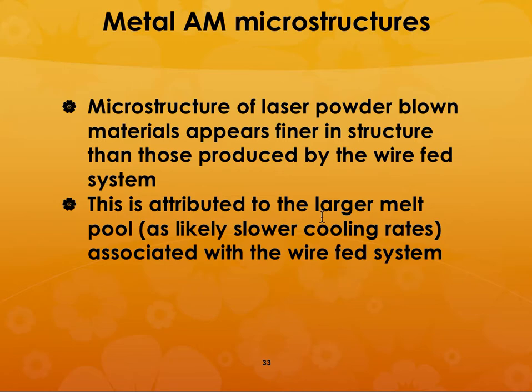In this case, the laser powder blown material appears finer in structure than those produced by the wire fed system. And they speculate that it is because it has got a larger melt pool, with slightly slower cooling rates in the wire fed system than in the other case.